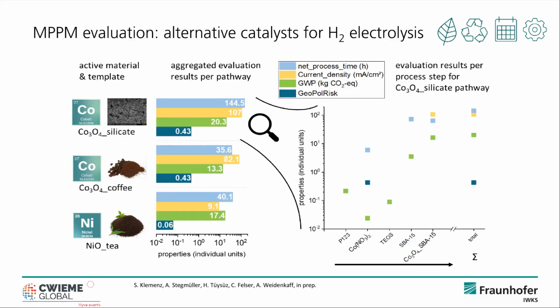So we had a collaboration with colleagues from the Max Planck Society, and they came up with new synthesis ways and new materials for these electrolyzer catalysts. I've stated 3 different materials here, or 3 different synthesis pathways, resulting in cobalt oxide that was templated, so synthesized with a commercial silicate, SBA15, a cobalt oxide synthesized along with used coffee, so ground coffee powder, and a nickel oxide that was made with spent tea leaves, also in powder form.